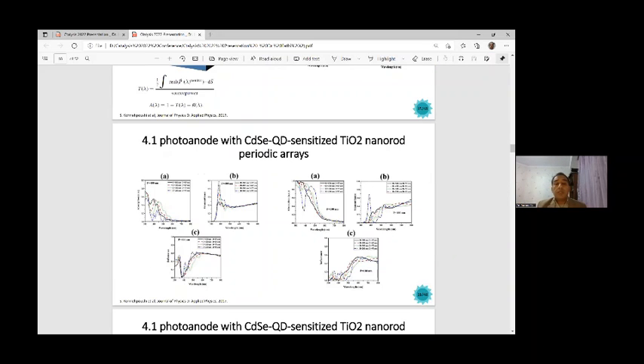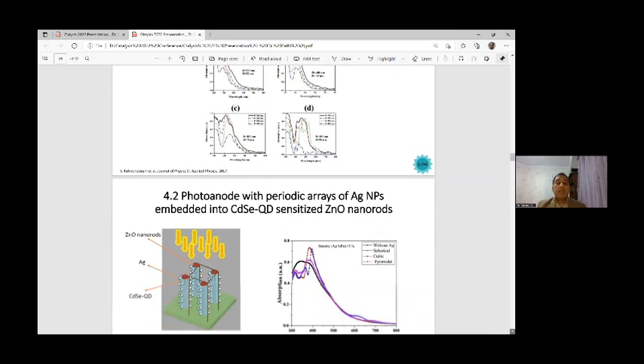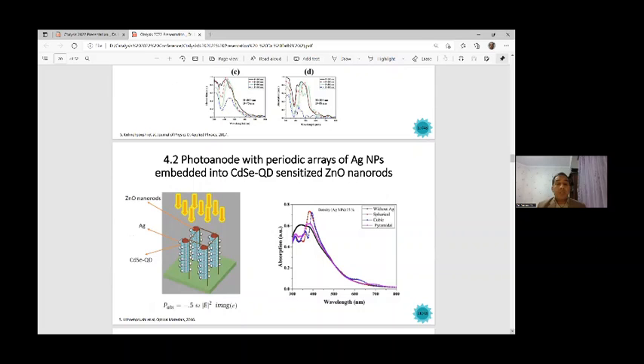You can see in these pages the absorption spectrum for various geometries and dimensions of the discussed structure. Say, a photoanode with cadmium selenide quantum dot sensitized TiO2 nanorod periodic array. At the next stage, on this page, you can see another arrangement: a photoanode with periodic arrays of Ag nanoparticles embedded into cadmium selenide quantum dot sensitized ZnO nanorods. We use here ZnO semiconductor nanorods sensitized with cadmium selenide quantum dots, and we use silver nanoparticles for improving the absorption of sunlight. This is the second photoanode material structure that I mentioned above.